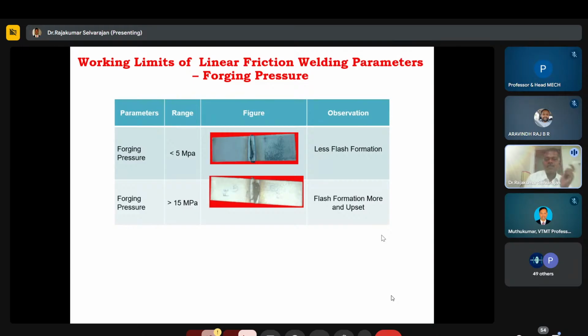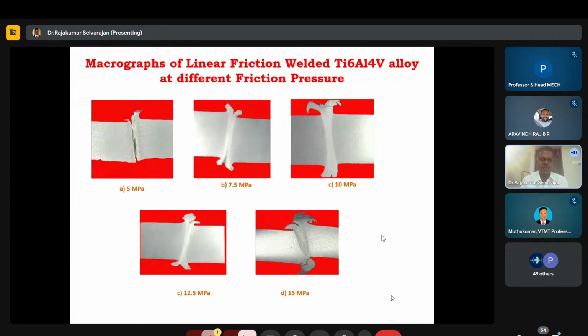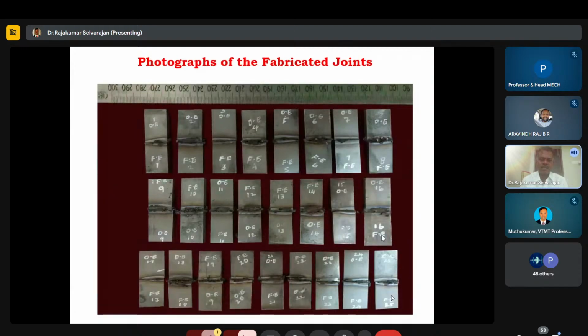And then the working limits for the forging pressure: 5 megapascal, and less than 5 megapascals gives less flash formation, and above that more flash formation and upset also. Within the range we can do some experiments at 5 megapascal, 10 megapascal, 12.5 megapascal. You can see that at 15 megapascals, the amount of flash and the regions also deviated. So within that, with the combination of the process parameters, we have to fabricate the joints.